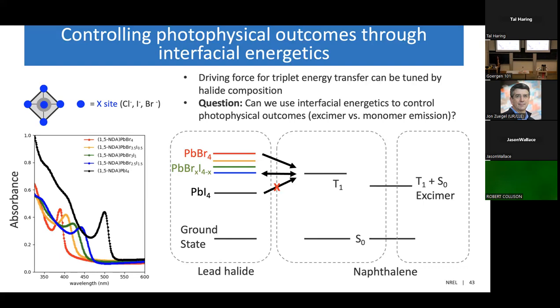So for the pure bromide system, which is shown in red, we have an exciton transition close to 400 nanometers. And then for the pure iodide system, we have a much lower energy exciton around 500 nanometers. And then the resulting interfacial energy level alignment looks like this, where for the pure bromide system, we have a large energy driving force for triplet transfer. For the pure iodide system, that process is unfavorable. And then for some of these intermediate bromide to iodide compositions, we may reach something of a resonance condition across this interface.